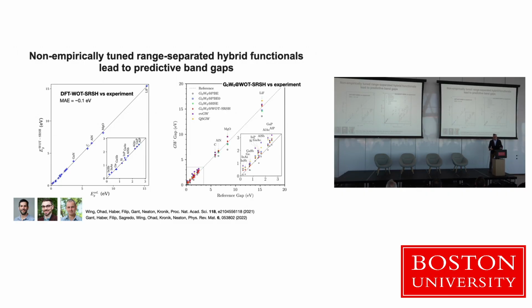And the other sort of state-of-the-art theory in this space is GW. I showed you some GW results earlier. And what you can do is you can use this functional as a starting point to do perturbation theory. And what you find is that there's zero perturbation. So the GW correction is zero, or small, and that suggests that you're basically done without the GW calculation.